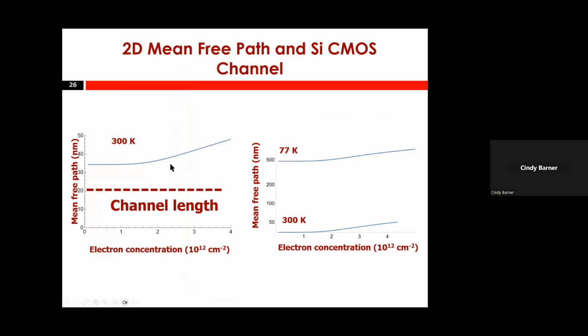And this is mean-free path in silicon. It's 300 Kelvin, and it's 77 and 300. And this is the channel length, typical channel length. Let's say GlobalFoundries, 20 nanometer SOI process, beautiful process, a dream to have, 20 nanometers. Even 3 nanometer technology for TSMC, channel would probably be around 18 nanometers. But it is shorter than the mean-free path. So this physics is very important there.